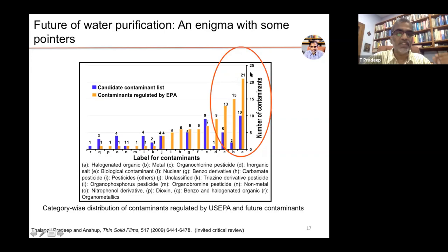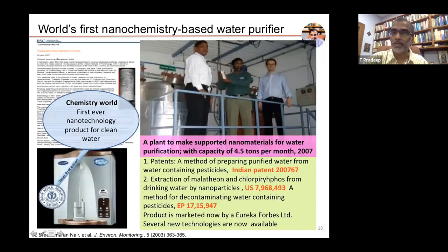For example, 21 species regulated in drinking water are halogenated organics. 15 of them are metals, etc. Many others are coming up as candidate contaminant list. And it is possible that by chemistry of certain kind, we can remove these halogenated organics. So that is what we found long ago and resulted in some patents. So this was the first plant that we made to have noble metal supported nanomaterials for removing pesticides from water at a very, very low concentration. This product was sold, when the last statistics was taken, about 1.5 million pieces.